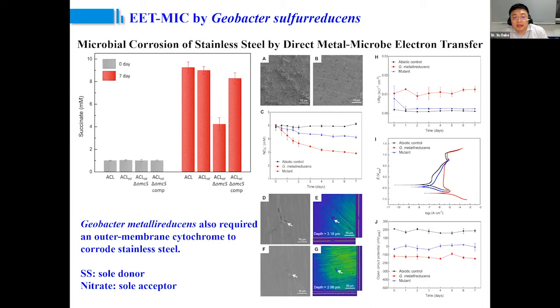And as I mentioned, fumarate is the only electron acceptor. So we checked the succinate concentration. When fumarate obtains electrons, it changes into succinate. We can see that when we delete hydrogenase, there's no significant difference in fumarate reduction. But when we delete OmcS, the fumarate reduction significantly decreased. And if we complement the OmcS gene back, they recover their corrosivity, so they recover the reduction of fumarate to succinate. So we first submitted this paper to PNAS, and the editor raised a concern.